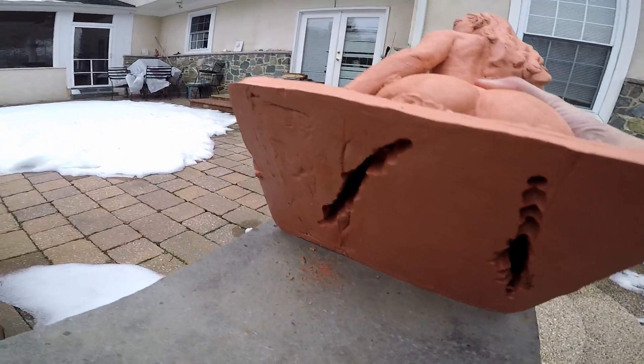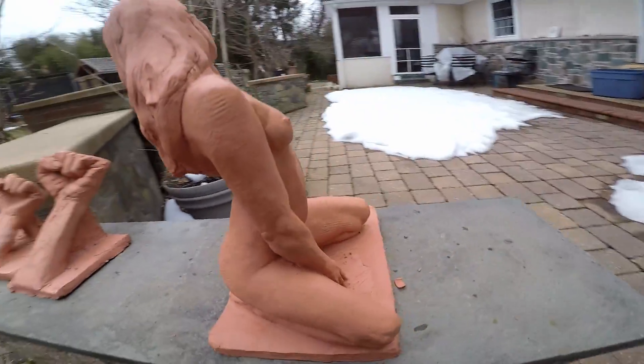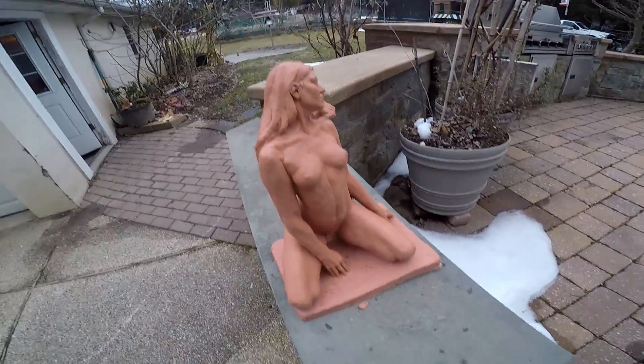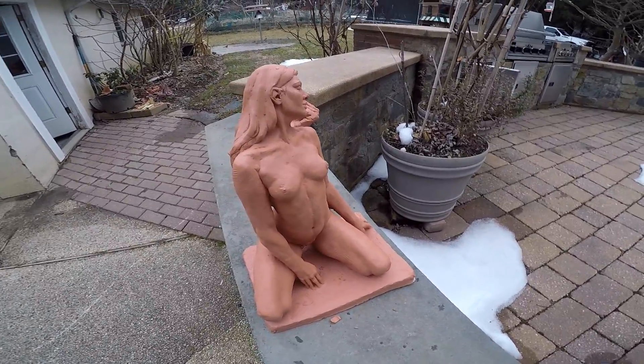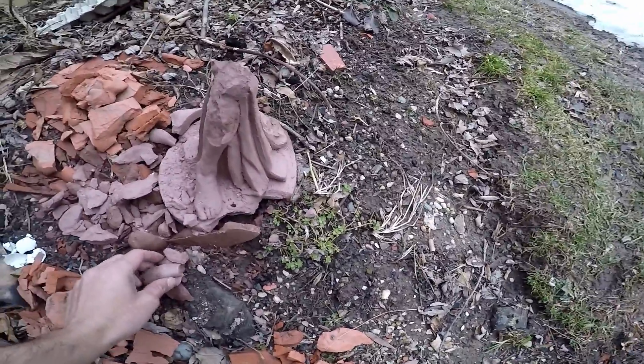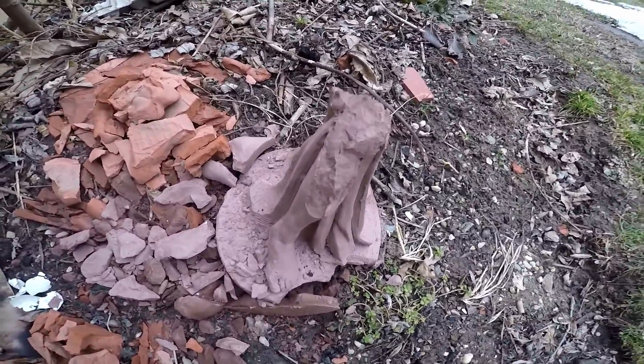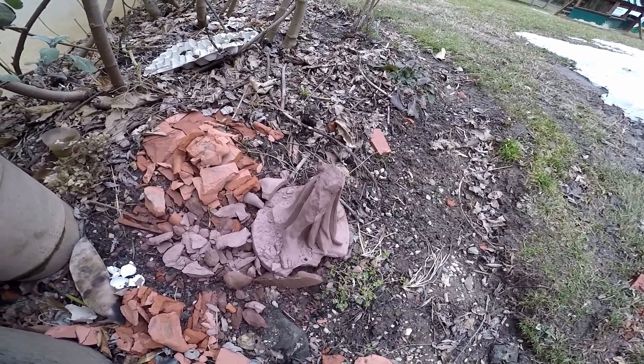Those are the holes I dug to get just a little bit of clay out — we'll clean that. This is a sculpture that's strong enough you could leave it outside and it wouldn't break. The only way it'll break is if you drop it from a certain point. That's kind of an amazing firing. See, this is that standing figure that I did — now it just joined the garden. This one exploded almost right away. It was very disappointing because I worked on it so much, but the firing was completely my fault. I fired it too fast, and that is the key — you want to fire things really slowly in the kiln.